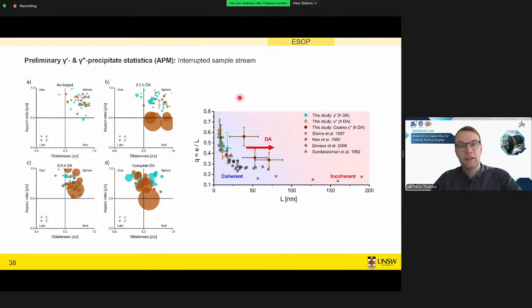So this is a comparative plot on the right-hand side with some other studies, mostly based on TEM, but we can separate our gamma prime and gamma double prime into small particles, which fit very nicely into this previously observed trend. And then our coarse gamma double prime structures, they do not fit, which is an indication that these particles are already coarsening and therefore have lost their coherency to the matrix. And that's really important for this phase, because once gamma double prime has lost coherency, the contribution to the yield strength is very low.